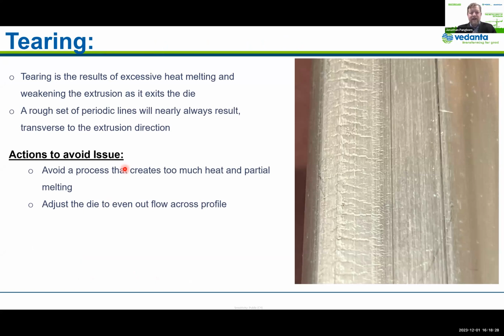Let's start by looking at tearing. And this is important to touch on, not because it's necessarily the most common issue, but I believe it's not always well understood. To me, tearing is specifically a temperature-related phenomenon, whereby we actually are getting the initiation of melting, or at least very, very close to it. And it's characterized by this type of appearance, where we have these lines transverse to the extrusion direction, where the metal is actually starting to come apart. This is quite different than many of the other phenomena we'll look at. But basically, this is something we see, especially on sharp corners of dies and so forth, or at screw bosses. And in order to avoid this, we really need to look at the temperature control locally at that detail, and perhaps make adjustments to the process to avoid this.